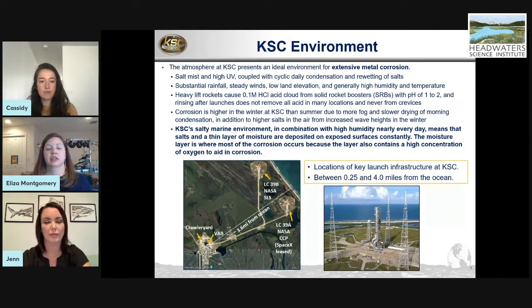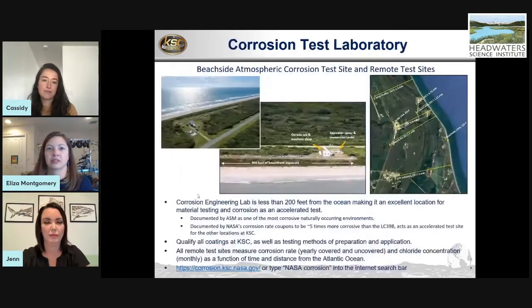And then you also get increased wave heights in the wintertime because the seas are just rougher naturally. So you get more salts in the air and then it corrodes. And because of where our environment is located, the humidity is relatively high all the time, so you get a light layer of moisture on the surface at all times. And that is literally a light layer of corrosion-like environment. So yeah, that's just the way it is.